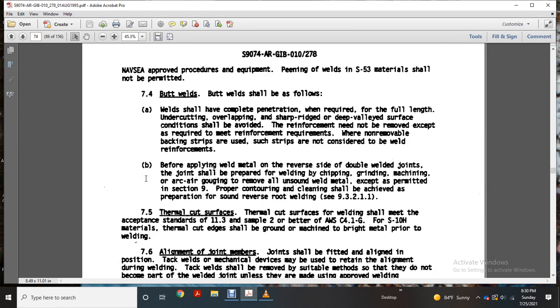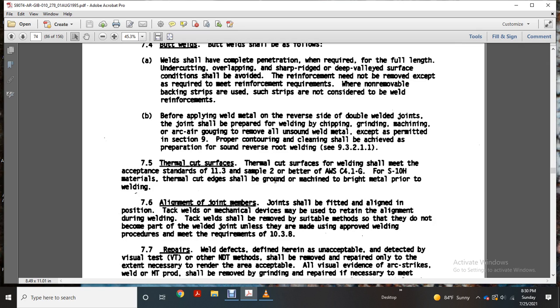93211, thermal cut surfaces. Thermal cut surfaces to be welded shall meet the acceptance standards of 11.3 and sample 2 or better of AWS C4.1G, and S10H material. Thermal cut edges should be ground by machine to bright material prior to welding. Alignment of joint members: joints should be fitted with alignment in position. Tack weld or mechanical devices may be used to retain the alignment during welding. The tack welds should be removed by suitable methods so that they do not become part of the welded joint unless they are made using an approved welding procedure to meet the requirements of 1038.